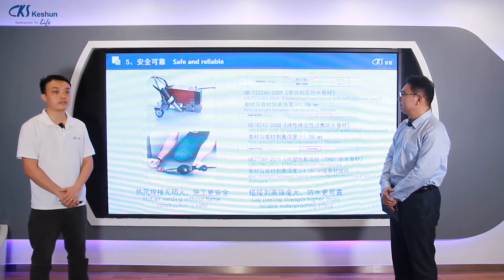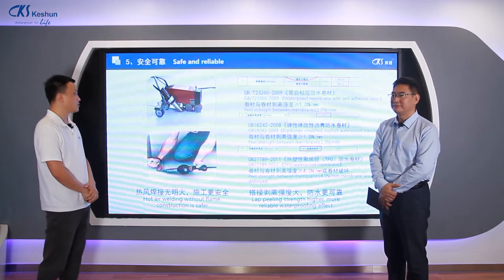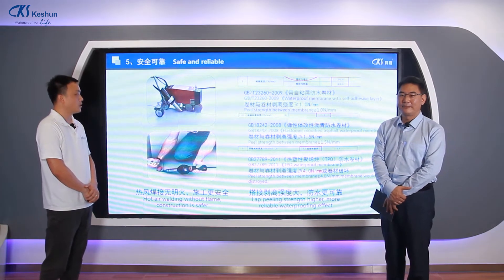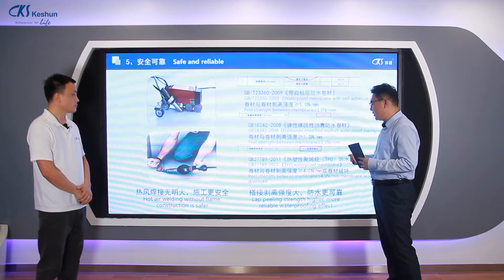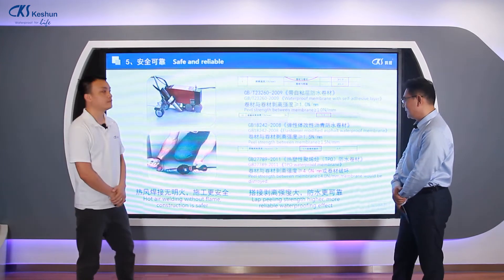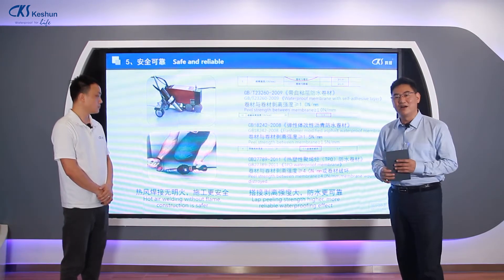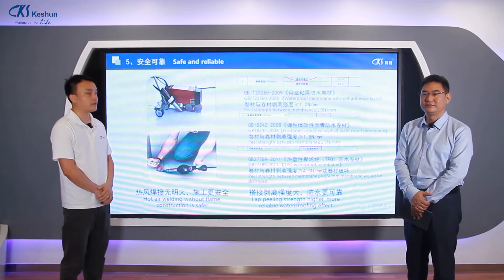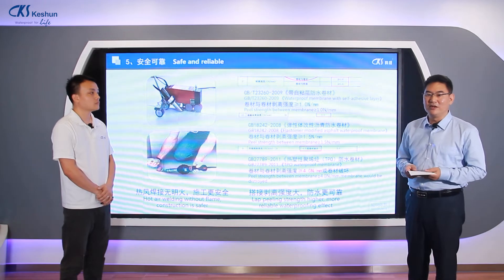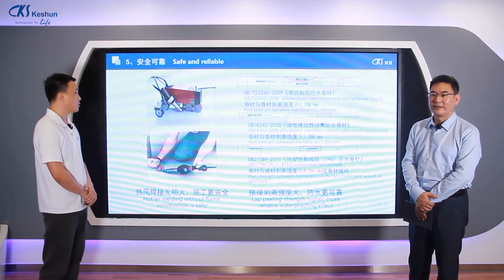We are going to talk about the safety of the TPO. The peel strength of the overlap seam for bitumen membrane is 1.5 N/mm, while for TPO waterproof membrane the overlap peel strength is greater than or equal to 4.0 N/mm — so the overlap strength of TPO is far superior, making waterproofing more reliable. Additionally, TPO membrane uses hot air welding for installation with no open flame, so it is safer.